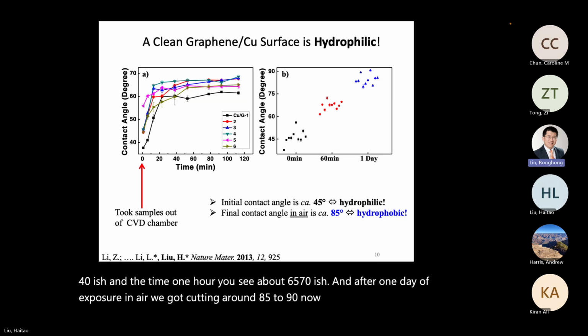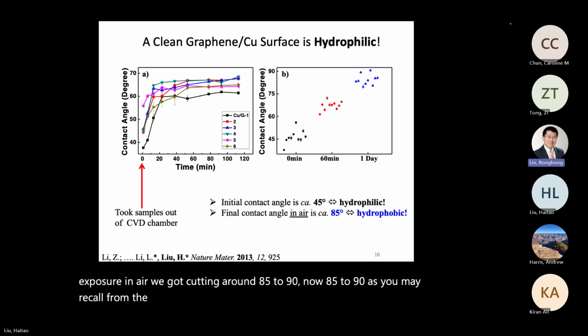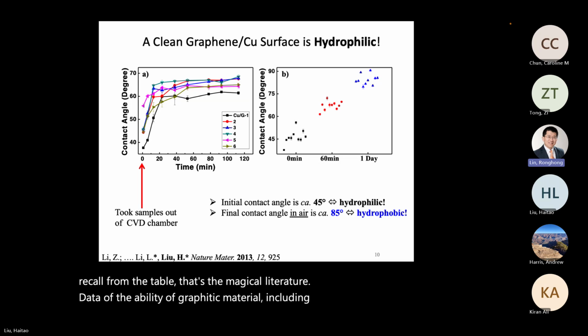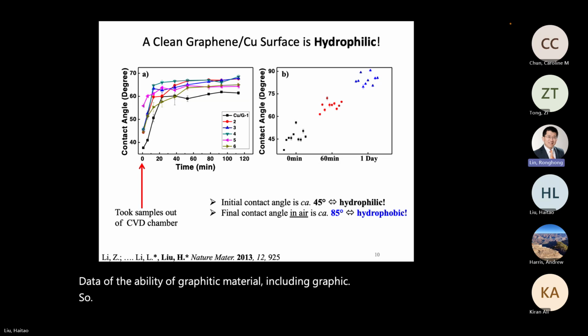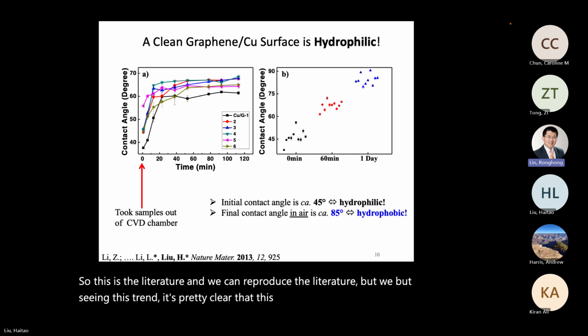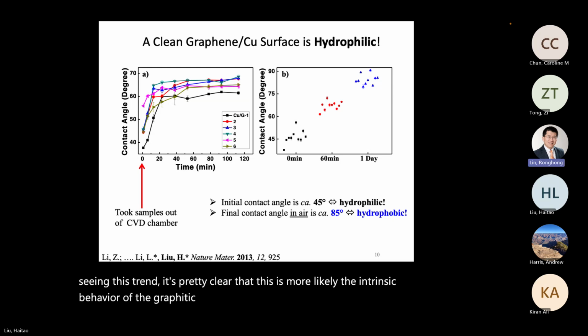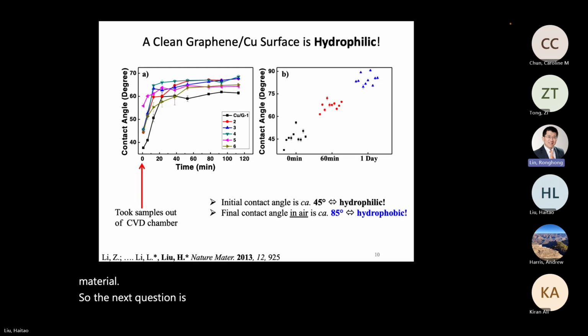Now, 85 to 90, as you may recall from the table, that's the magical literature data of wettability of graphitic material, including graphene. So this is the literature, and we can reproduce the literature. But seeing this trend, it's pretty clear that this is more likely the intrinsic behavior of the graphitic surface, specifically the graphene on copper material. So the next question is, what is happening?